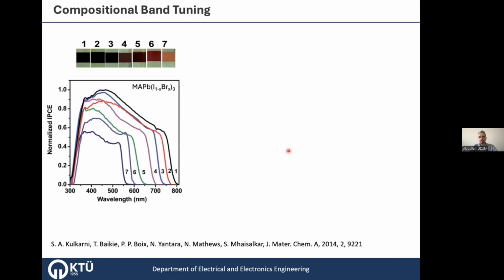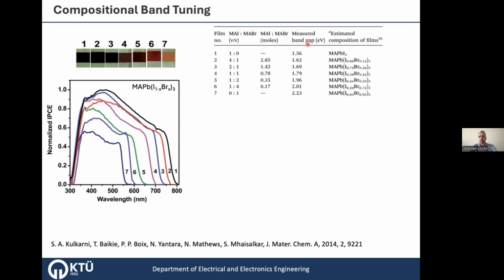And here is a systematic change of the band gap of methylammonium lead iodide by adding bromide content to it. And here is how they add the bromide content. You see that as the bromide content increases, the absorption decreases toward lower wavelengths because of the increasing band gap. And if you check the color, and produce it really, you see that the color changes from black-brown to orange with full bromide, and the band gap changes from around 1.55 to 2.23. This is methylammonium lead iodide and methylammonium lead bromide mostly here.